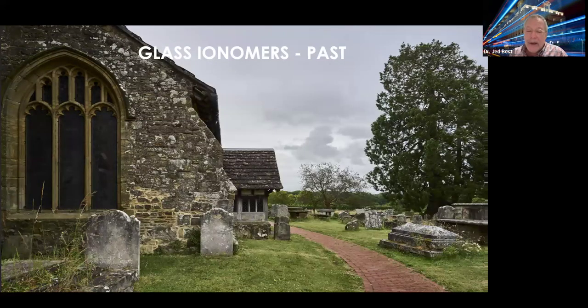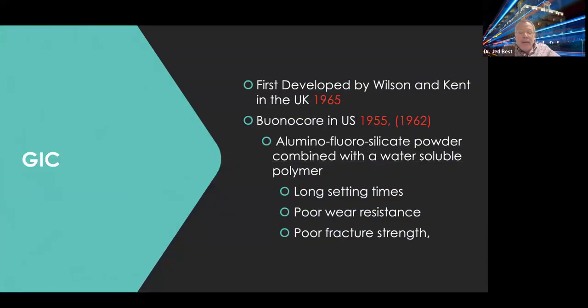So let's talk about glass ionomers. Now let's talk about their past. Were they great when they first came out? Well, glass ionomers have never been super popular in the United States. We should note that Buonocore in the United States developed acid etching roughly in 1955 and released the first resin composite commercially roughly around 1962. Glass ionomers weren't developed until 1965 by Wilson and Kent in the UK. And what are they? Well, they're an aluminofluorosilicate powder that's combined with a water-soluble polymer. The problem is it has long setting times, poor wear resistance, and poor fracture strength.